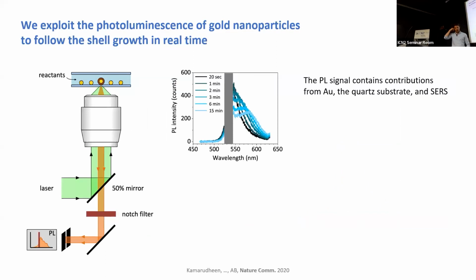And so we thought, well, we're shining a laser during this 15 minutes irradiation. We are heating up the nanoparticle. Why don't we collect the inelastic light scattered back? So why don't we look at the photoluminescence or any other signal that is coming out that is inelastically scattered? We cannot collect the green laser, otherwise we fry our detector, but we're going to filter this 532 nanometer and look at anything that is being reflected back. And if you do that during the 15 minutes laser irradiation, you do see a trend, but you don't really understand anything of what's going on.